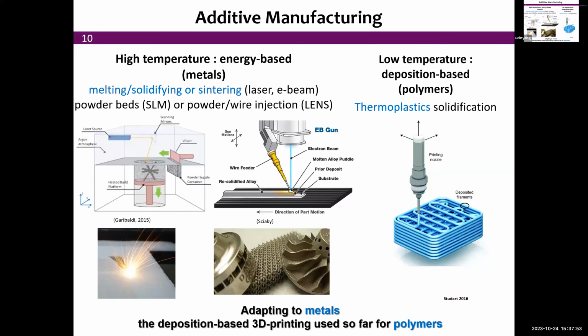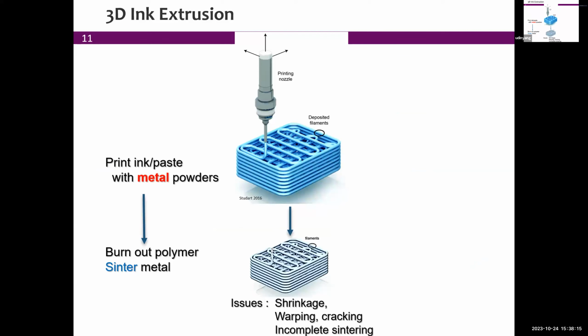And the idea here is to adapt to metals what is currently done for polymers, and that is this ink printing that I and many others in the field have been exploring as a way to get the advantages of low temperature printing, and then only after the structure has been made, transform it to metallic structures. So for the case of metal powders, if we load that ink with metal powders, you can extrude that suspension of metal powders and fluid into a 3D printed structure. You can burn out the polymer, sinter the metal, and you end up with a metallic structure.